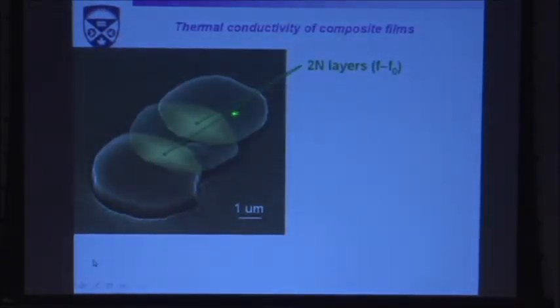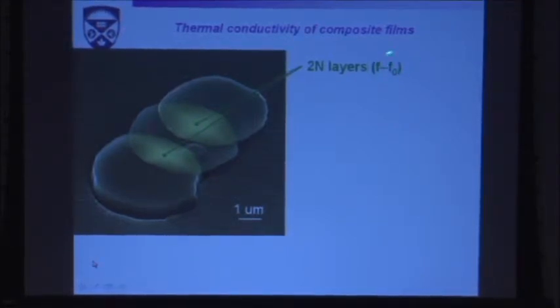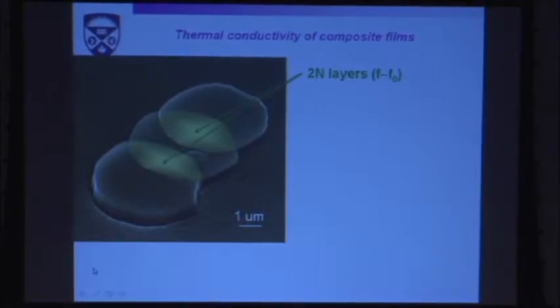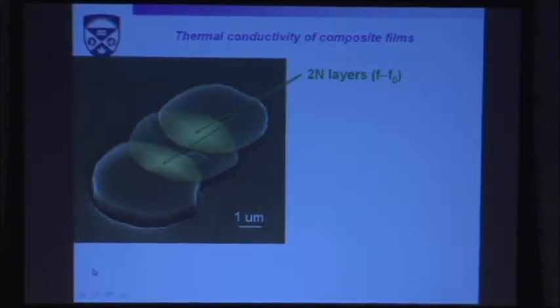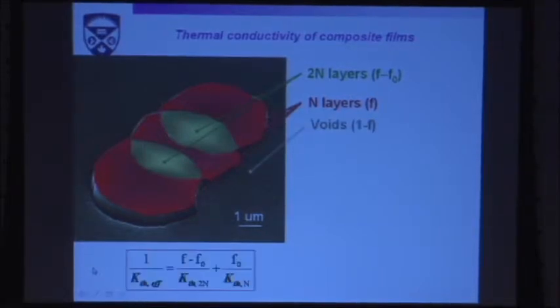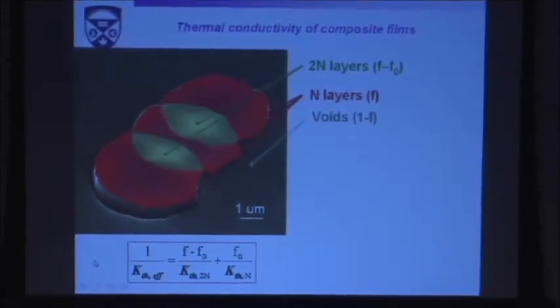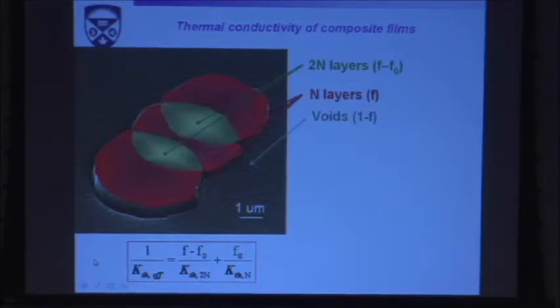But anyway, there are the overlaps that, according to percolation theory, where the density of overlaps is F minus F0, is the concentration of overlaps that limit your thermal conductivity. When you overlap layers, there you have a bottleneck for thermal conductivity. While the n layers limit the thermal conductivity much less because they are thinner. And voids, of course, don't do anything. Edges can do something, however. So our model assumes that edges can be negligible, and that's an important point.